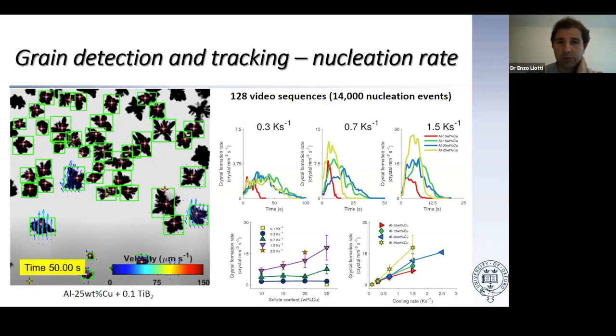For example, these graphs show that the formation rate, so the rate at which crystals form, increases with the cooling rate, and that's actually expected and known. But there is also a correlation between the cooling rate and the solute content. Strictly speaking, the formation rate increases with the cooling rate and the solute content, but the two are correlated. For example, increasing the solute content has an effect only when you increase the cooling rate. At a low cooling rate, essentially, it doesn't have an effect. This is a new finding that was found thanks to the very large amount of data that can be generated.